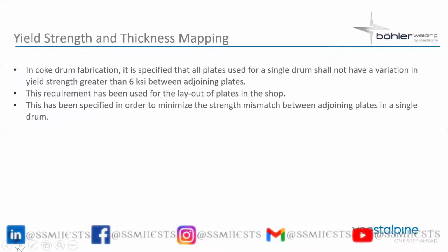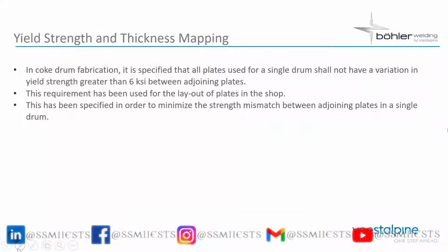So here the problem is that this bulging happens. What people found out in such an application is that because of the difference in yield strength between the weld metal, the weld seams, and the parent material, this bulging was happening. So not only in the welding part, but also in terms of fabrication, it was specified that for a single coke drum, there would be a mapping of the adjoining plates with the yield strength, and the layout would be made in such a way that there would be a variation of not greater than 6 KSI between adjoining plates. Can we go next?